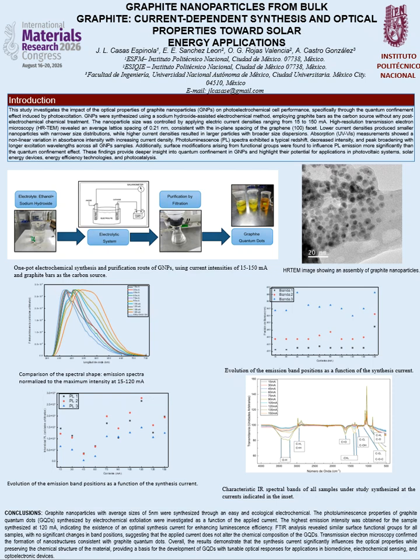Graphite nanoparticles were synthesized using a sodium hydroxide-assisted electrochemical approach in a single container, with graphite bars as the carbon source and current of 15 to 150 milliamperes. The GNPs were characterized by high-resolution transmission electron microscopy, infrared spectroscopy, absorption, and photoluminescence spectroscopy. HRTEM revealed lattice spacings of 0.336 nanometers and diverse particle sizes.